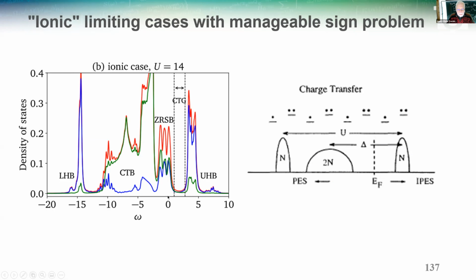And at the Fermi level, that is this zero here, we have states that are a mixture of copper and oxygen. They are the so-called Zhang-Rice singlet band. And red is the total density of states. So I will come back a lot later to this charge transfer gap. So this is what I mean here by this charge transfer gap. Here in this cartoon, it's just like this. Here I really mean the difference between these two bands. Okay, any question?